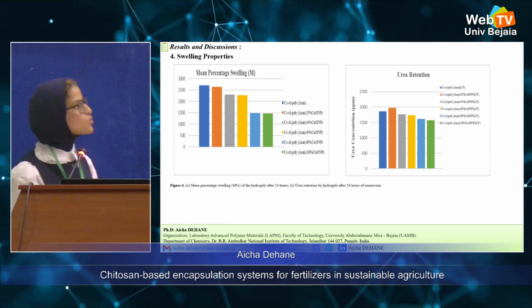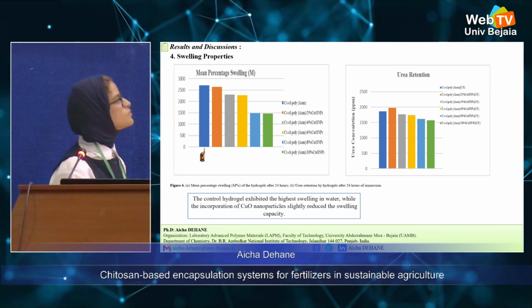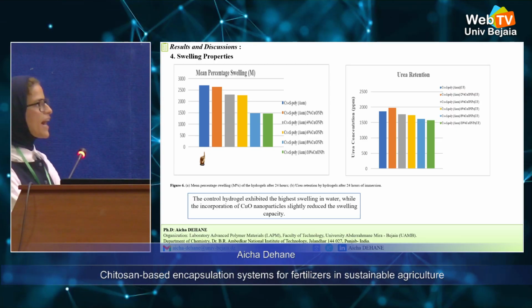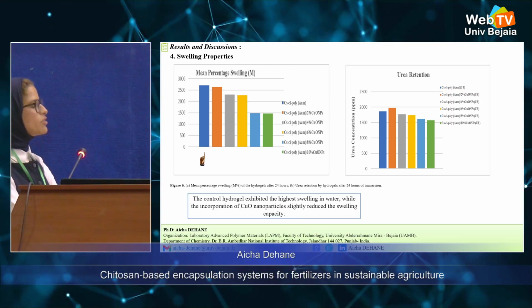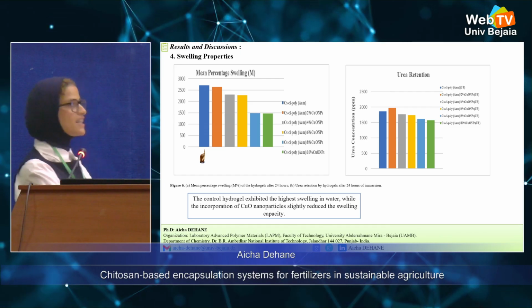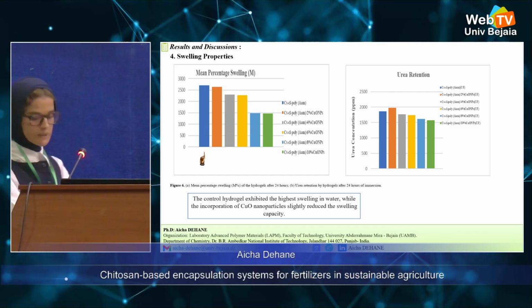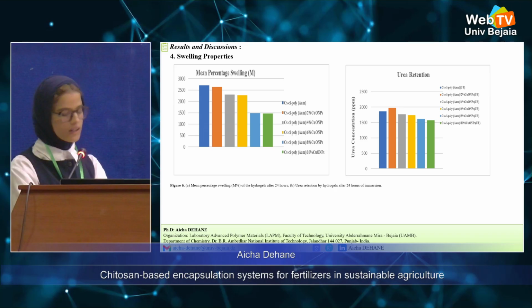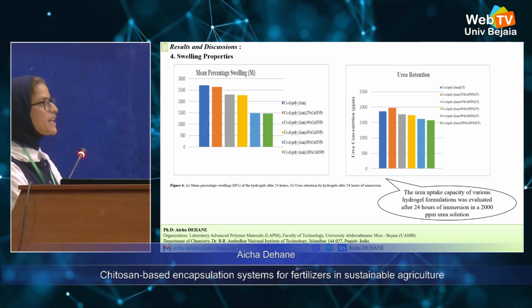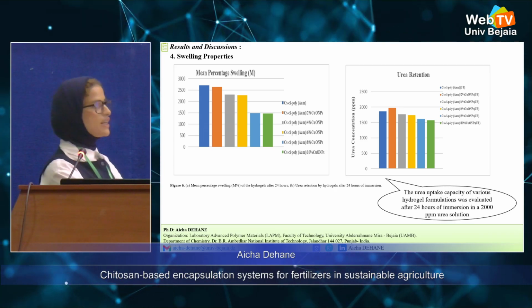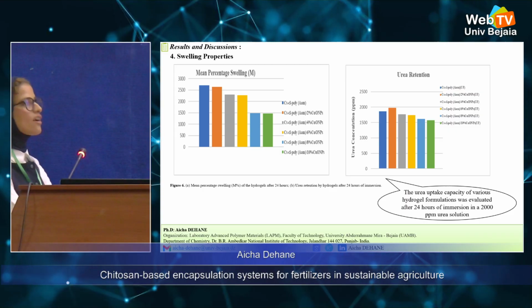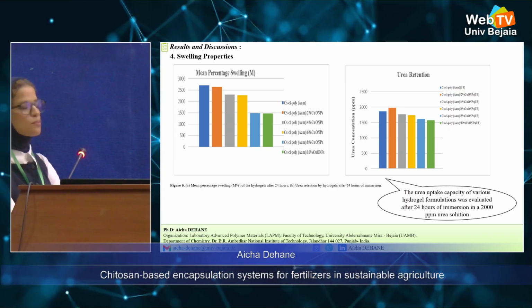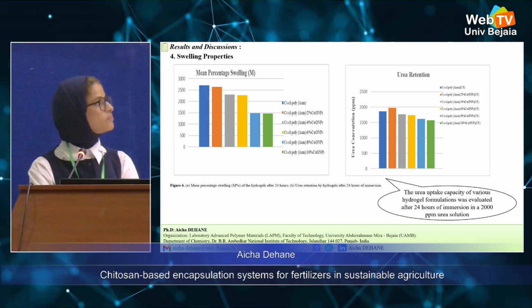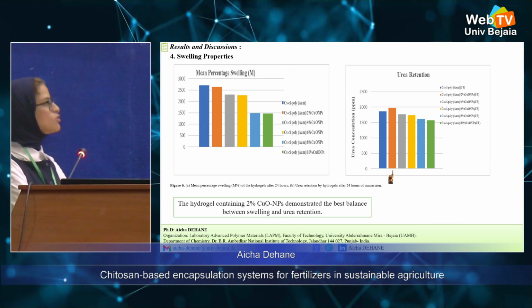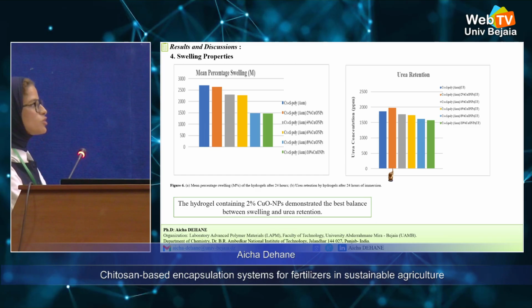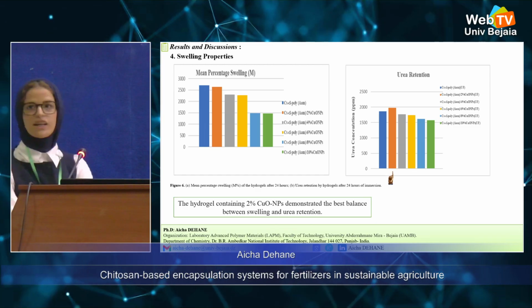Let's move to swelling properties. The control hydrogel has the highest swelling, while the incorporated nanoparticles slightly reduce the swelling capacity. The urea uptake capacity of various hydrogel formulations was evaluated after 24 hours of immersion in a 2000 ppm urea solution. The hydrogel with 2% CuO nanoparticles shows the best balance between swelling and urea uptake.